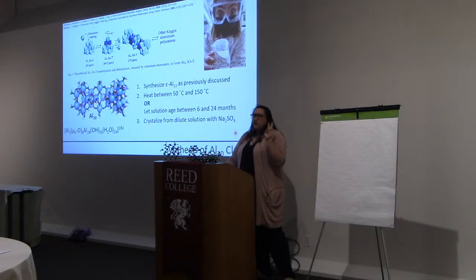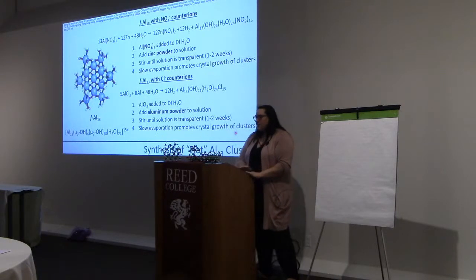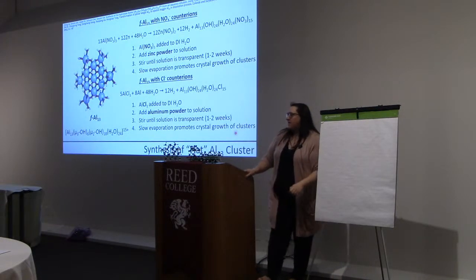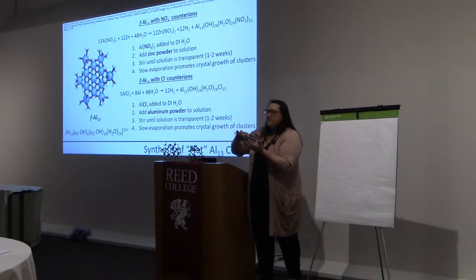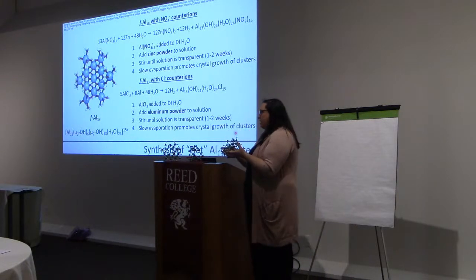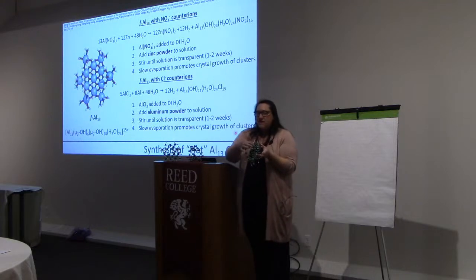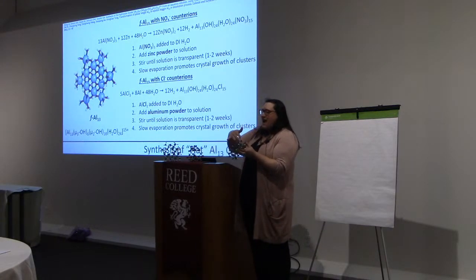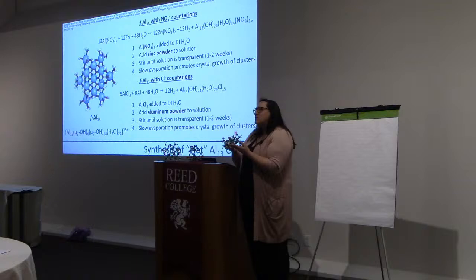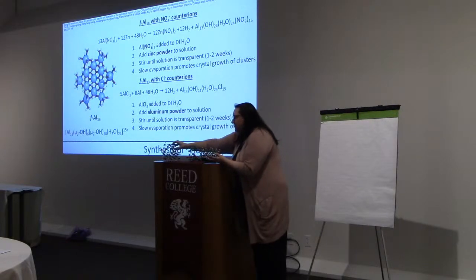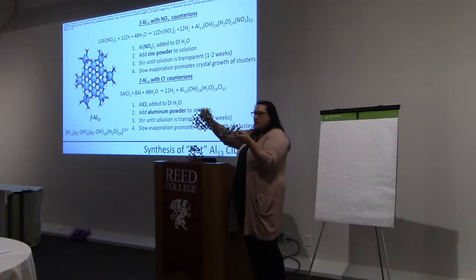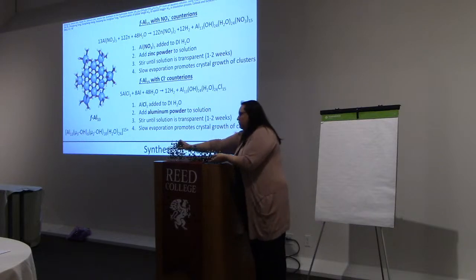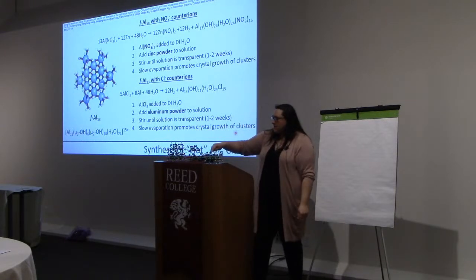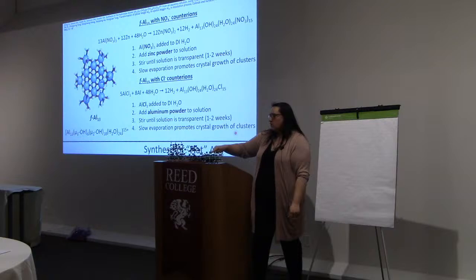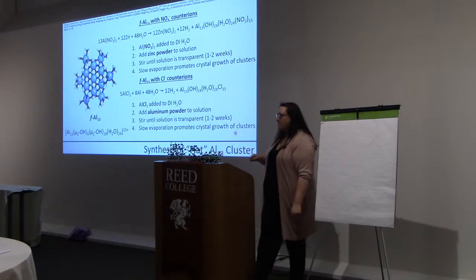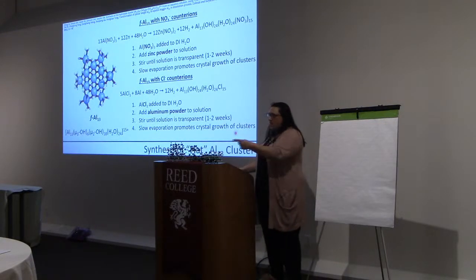So the third cluster that we've decided to synthesize is the flat aluminum 13. Here is the flat aluminum 13. The reason we call it flat is the center 7 are planar, but the outer 6 are up and down and up and down. So it's not really flat, but it's much flatter than our Keggin version. So these are our 2 that have 13 aluminums in them. This one got deprotonated, which is very common. I don't know where that proton got to, but it happens all the time in the samples and in these models.